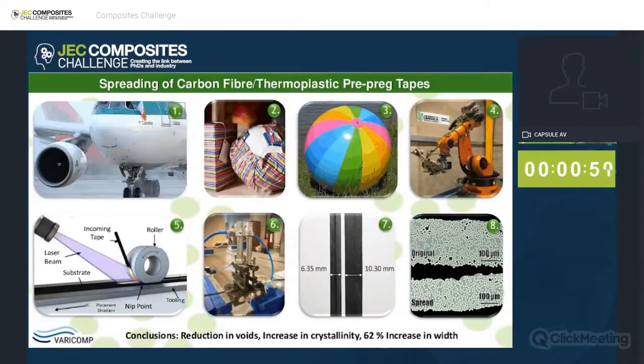We also completed crystallinity tests, and we found that the spread tapes had an increase in crystallinity, which is beneficial as increased crystallinity results in improved strength and improved fatigue performance. Further tests are required to see, does this spreading negatively affect the quality of the tapes at laminate level?